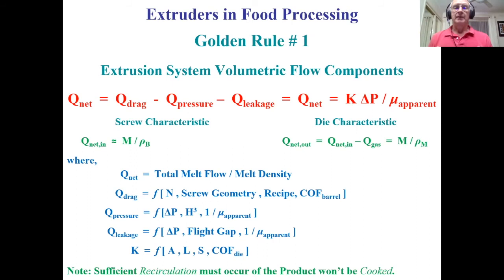Once that melt is formed and the formulation has been transformed into the fluid, it is pumped through the extruder die. And these fluids are very viscous. In terms of order of magnitude, a typical extrusion melt will have a viscosity of somewhere between 50,000 to 200,000 centipoise, or 200,000 times thicker than water. So very viscous fluid. And most of these fluids are being forced to flow through very small dies or orifices. As a result, the operating pressures required within the extruder are very high. It's not uncommon to see an extruder operating at 30, 40, 50 atmospheres of pressure. And this reflects both the high volume flow through complex small geometry, but also the very high viscosity of the materials being dealt with.